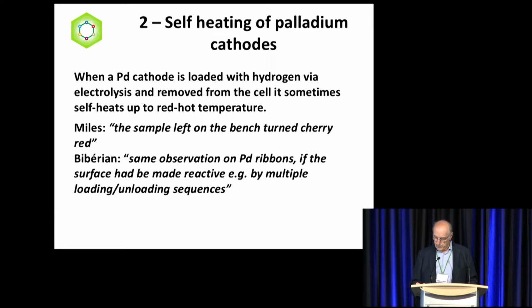Miles, for example, said the sample left on the bench turned a cherry red, and Jean-Paul Biberian had the same experience with the palladium ribbons if the surface was made reactive, for example, after loading, deloading several times. You have a very reactive surface, then it can turn red when you put this cathode in the air. I discussed this morning with Ed Storms, who has the same experience. Especially, he told me if this palladium is covered by a little bit of sulfur, then you are almost sure it will ignite.